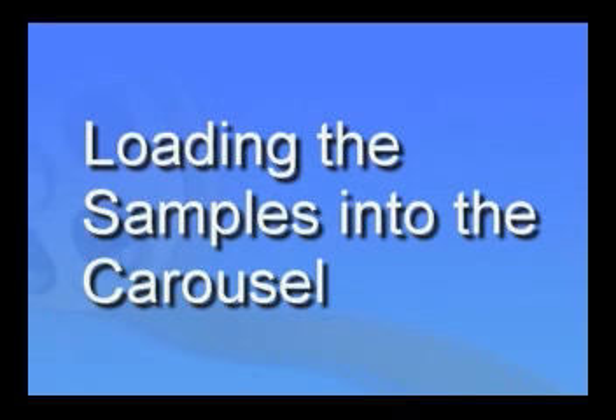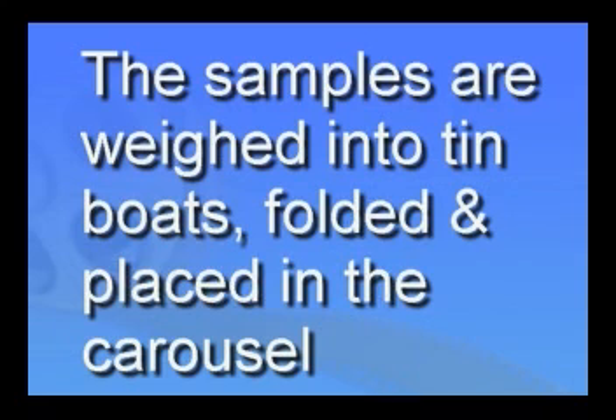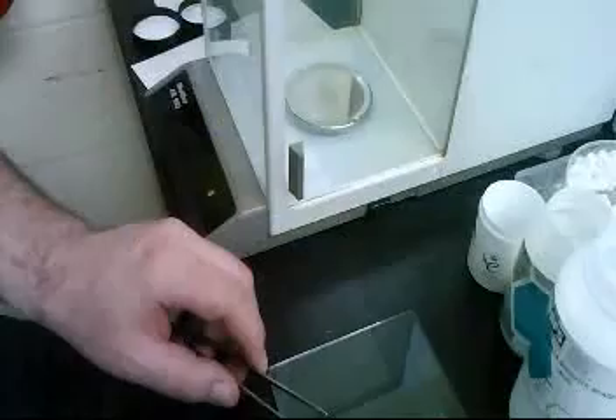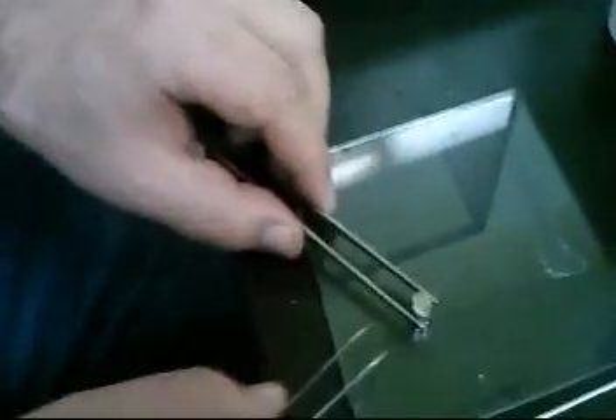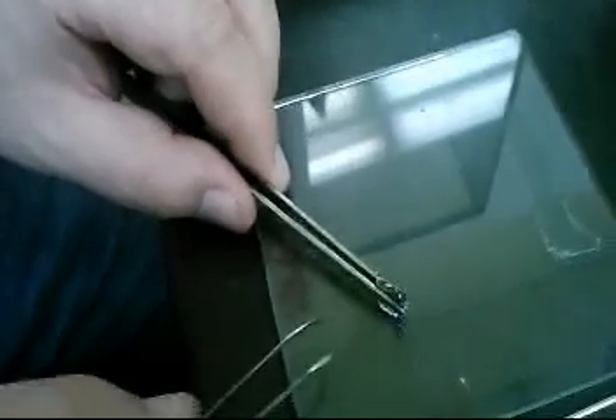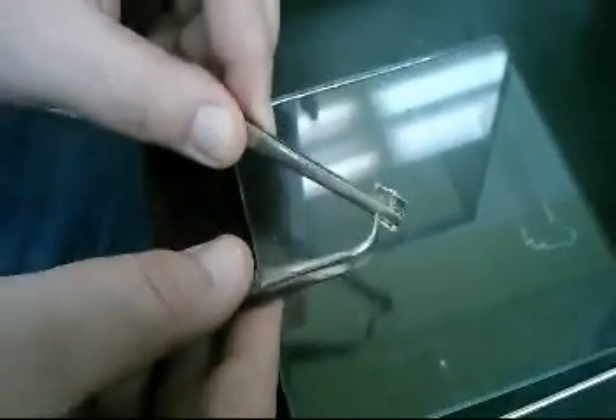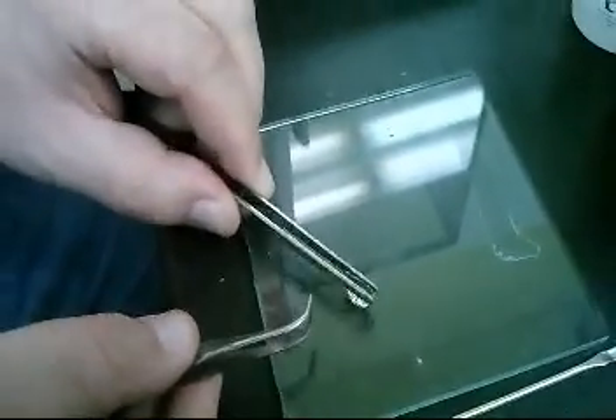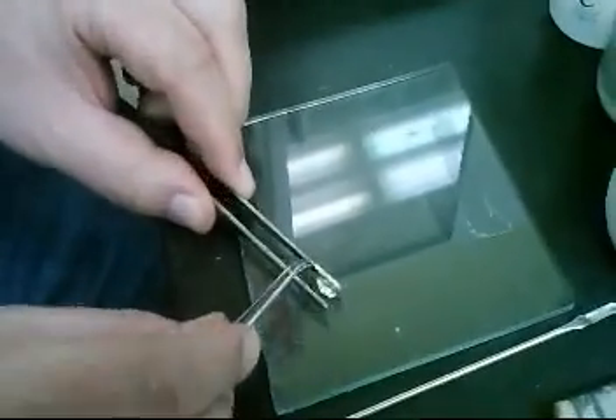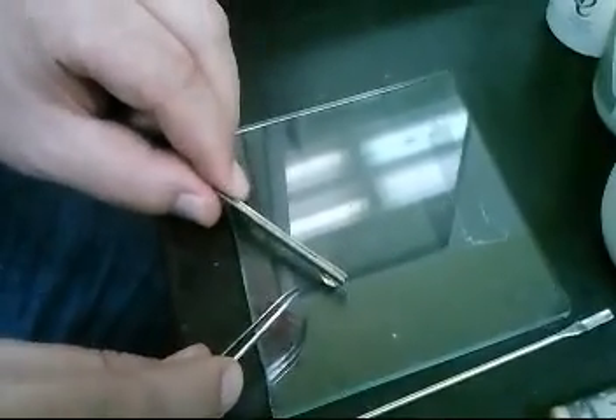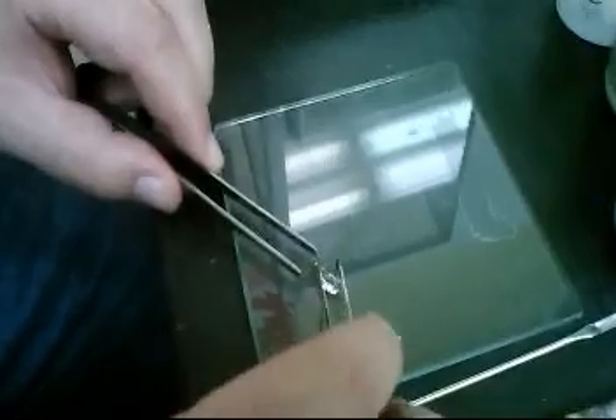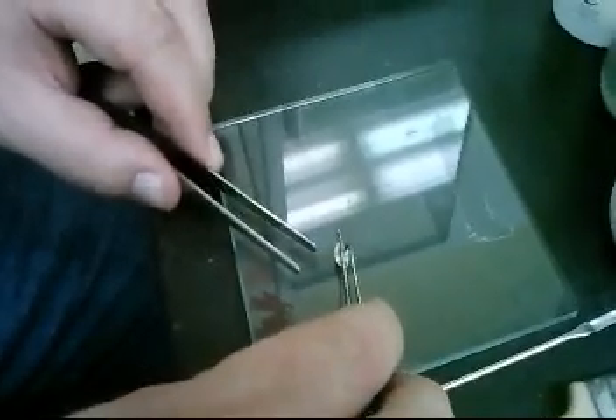Loading the samples into the carousel, folding the tin boats. The samples are weighed into tin boats, folded, and placed in the carousel. The sample is weighed in the boat. The boat is pressed with tweezers above the sample as shown, and then folded over. The boat is folded again until it finally appears as shown.